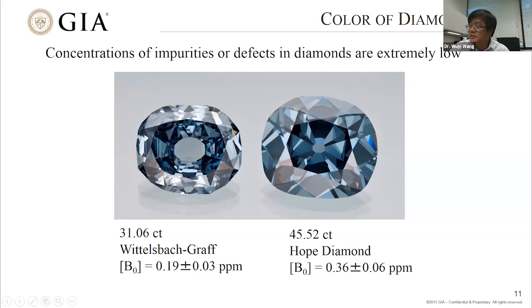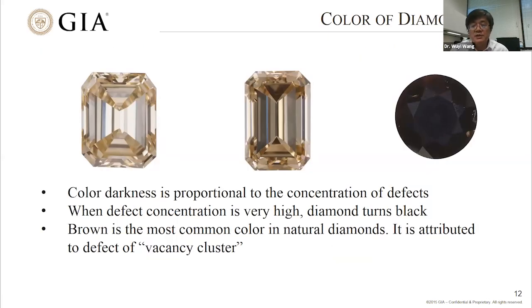So this is the first thing I want to emphasize. Second thing, what I try to show here, the three diamonds with a brown color. The left-hand side is a light brown, quite intense at the middle. And when the brown is so intense, the diamond even shows basically black color. Brown color is very common in natural diamonds, and it is not so attractive. It really decreases the value of a diamond in the market. After many years of research, finally we got to know the brown color is due to a defect called vacancy cluster. So the concept is the darkness of a color is proportional to the concentration of the defect in a diamond. For a specific color, if the concentration of a defect is very high, it will be darker.